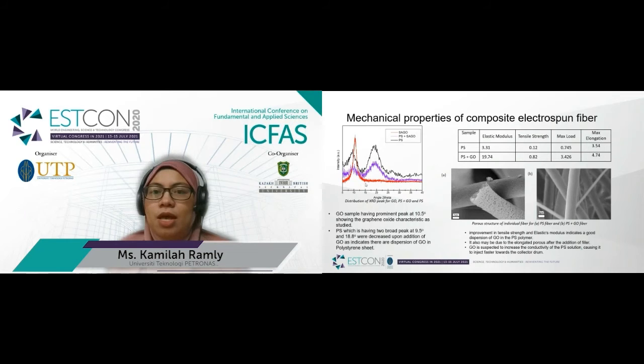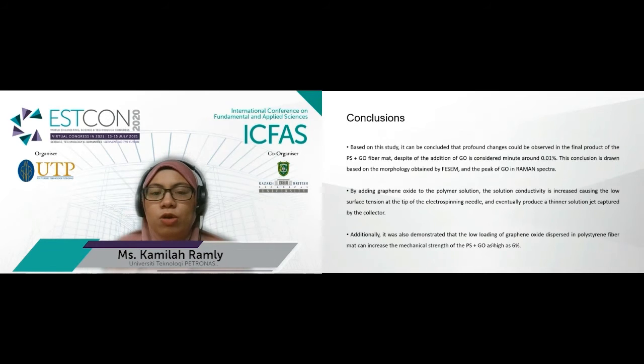polystyrene polymer. It may be due to elongated pores after the addition of filler, as observed compared to the initial polystyrene fiber. The GO is suspected to increase the conductivity of the PS solution, causing it to inject faster toward the collector. Hence, to conclude the presentation, based on this study, it can be concluded that profound changes could be observed in the final product of the PS-GO mat, despite the addition of GO being considered